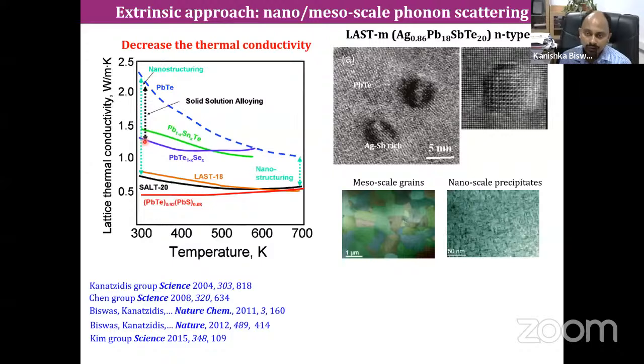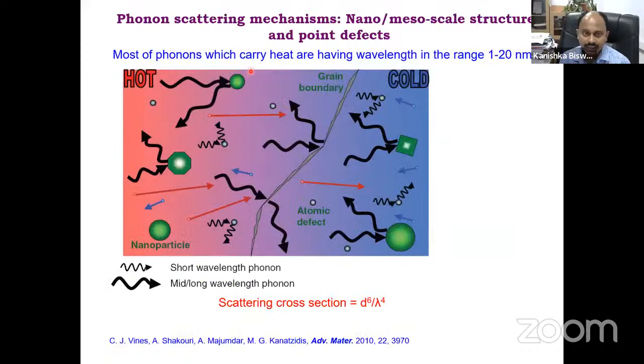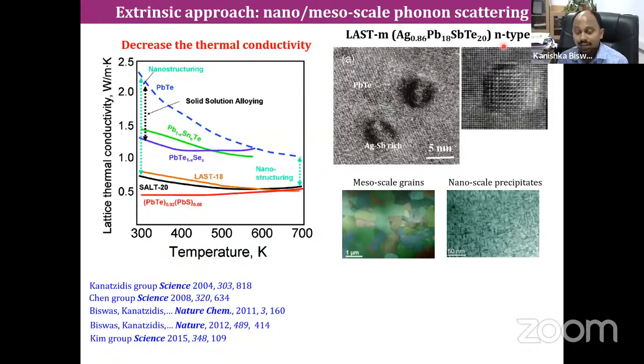Then in 2004, in this paper, they first showed that they had created this lead telluride sample with nanodots embedded in the lead telluride, in the size of say 1 to 20 nanometer. So these nanodots are exactly the same size as the phonon mean free path, which actually carries the heat. Once they created this nanostructured bulk material, I would say this is not a nanoparticle, but nanoparticles embedded in a bulk material. So I say this is a nanostructured bulk material, which shows almost a glass-like thermal conductivity, and which created a sensation, giving rise to a ZT of around 1.8 for the first time in lead telluride, and opened the gate for nanostructured bulk thermoelectrics.